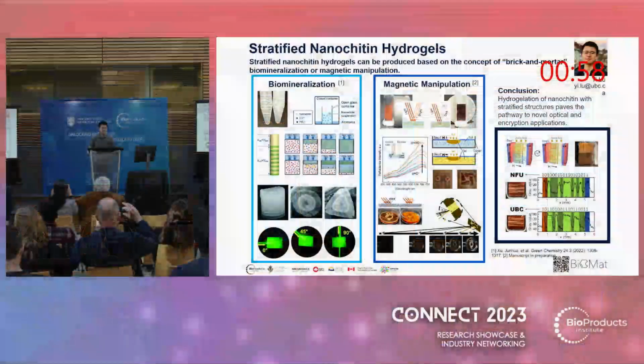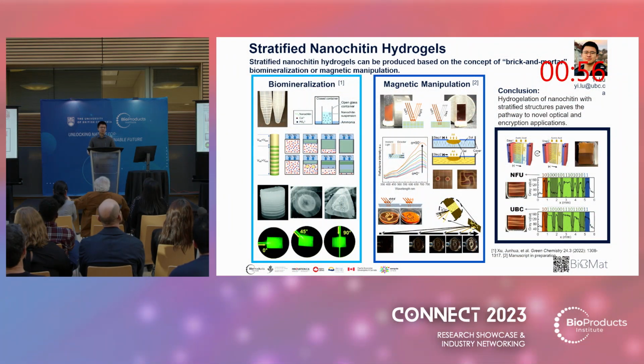So we extract chitin from crab shells and then further deconstruct them into nanoscale. We call them the nanochitin. The suspension of nanochitin can actually become a nanochitin hydrogel within a basic vapor bath. By controlling the hydrogelation process, we can create very interesting patterns that have periodical layers.